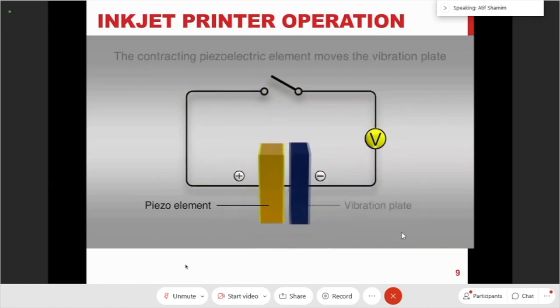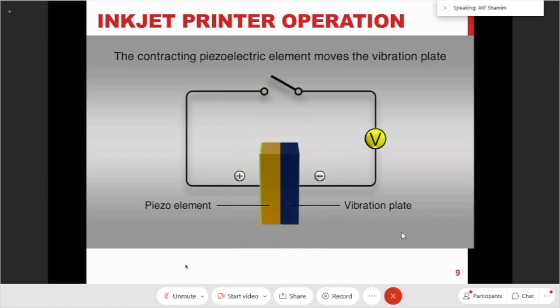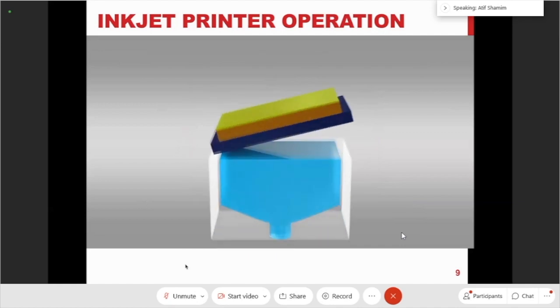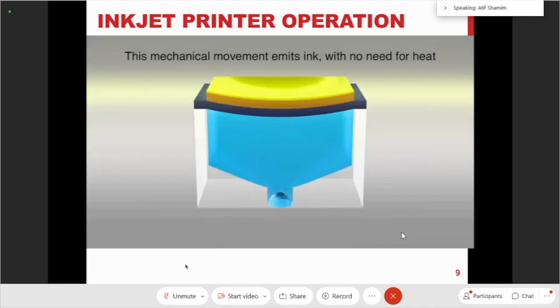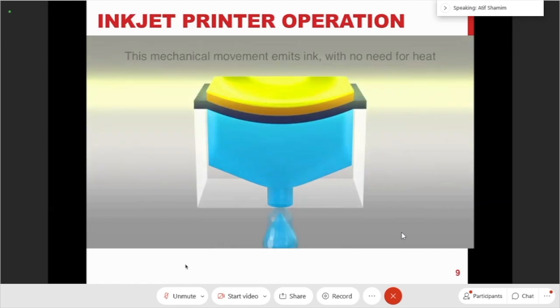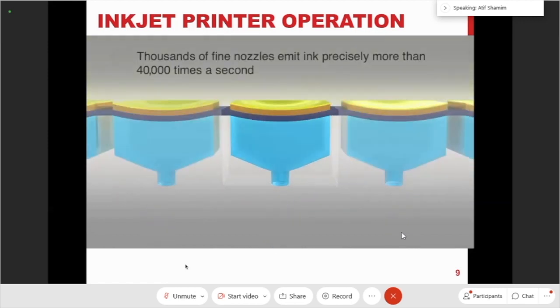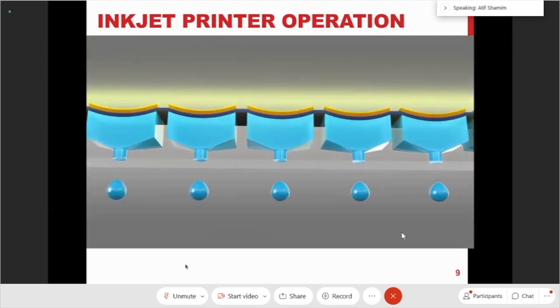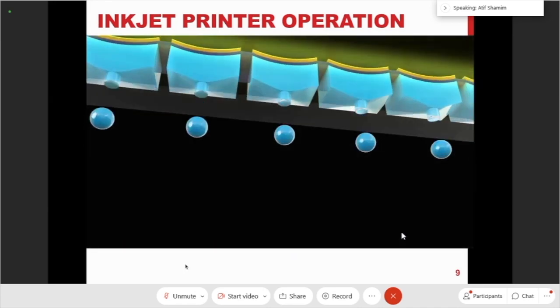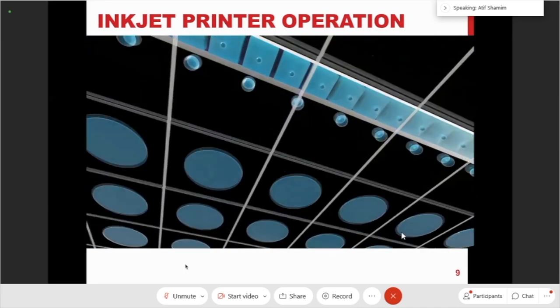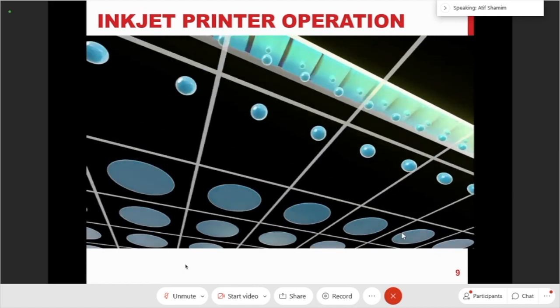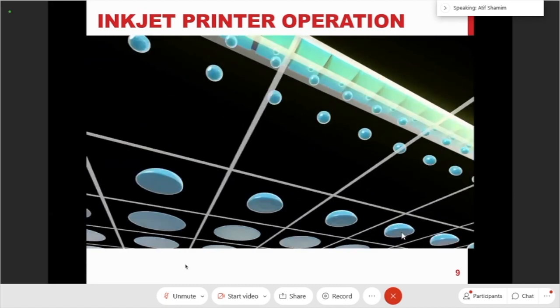So if you take one of these piezo elements and put it on a vibration plate, and you apply a voltage, or let's say an electric field, this will basically create pressure on a nozzle, right? Where it can eject the drops. And because of this fine control of the voltage waveform, you could eject drops of your own sizes. Multiple of these nozzles can be used together, and then you could print those. So this is how typically a piezo printer works. So very fine control through the applied voltage waveforms.